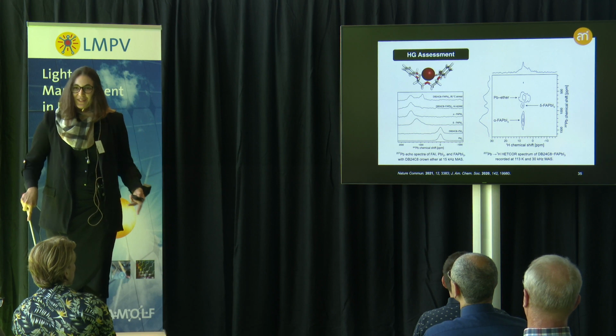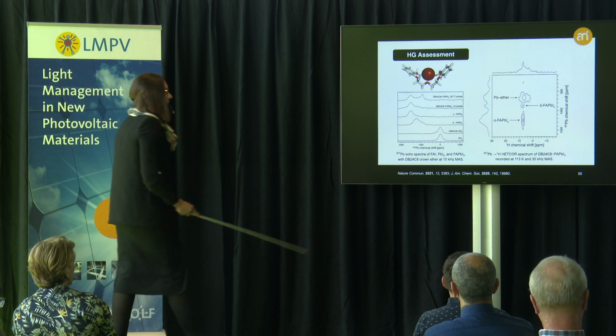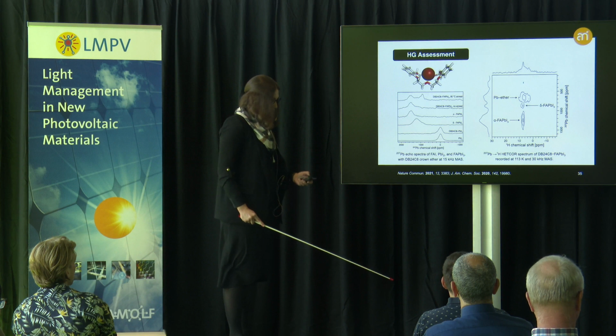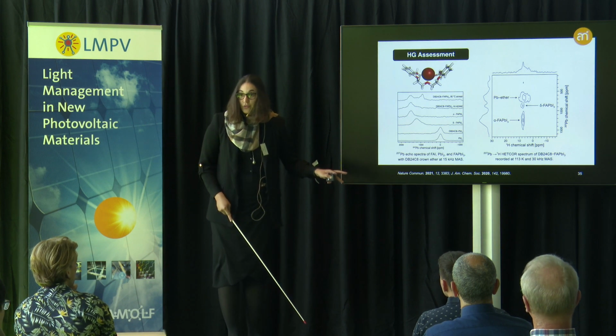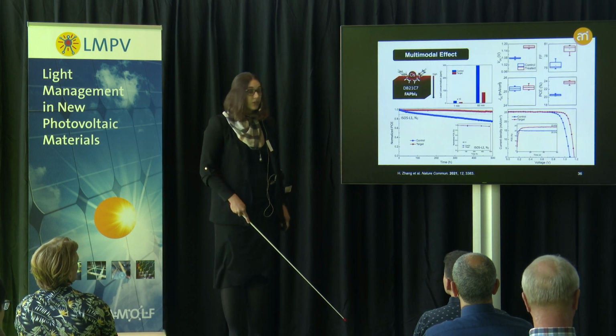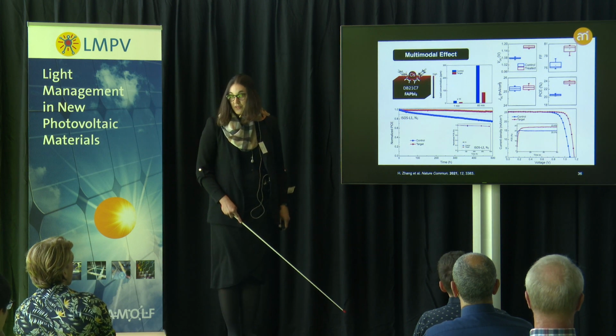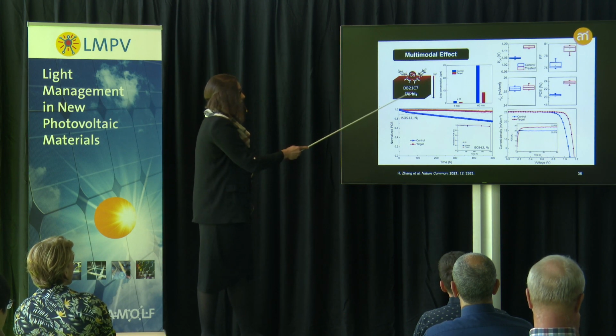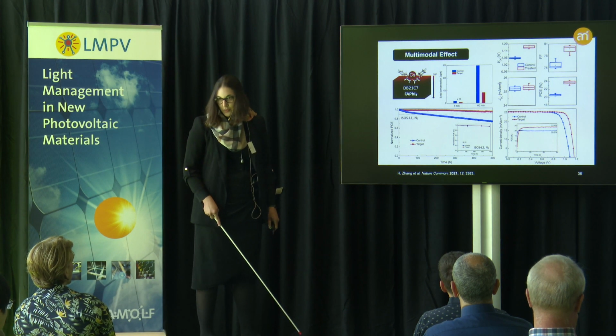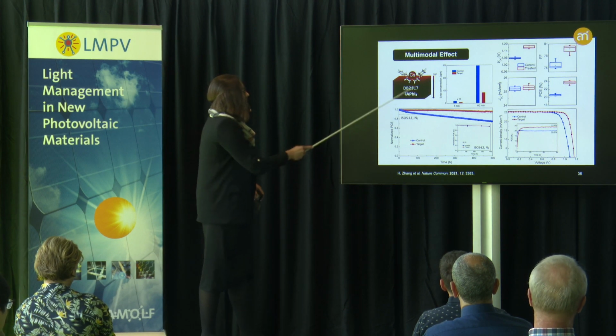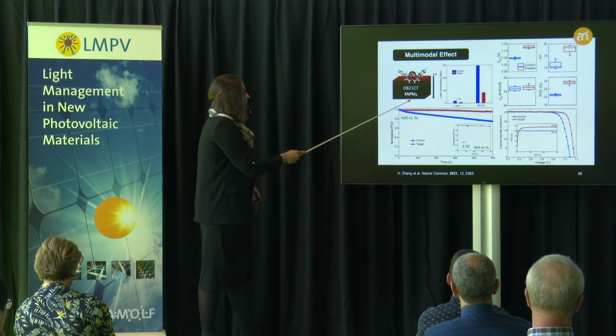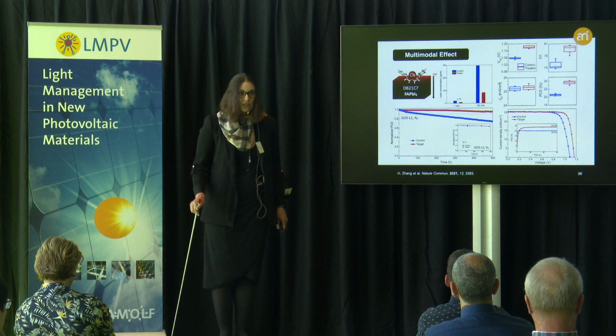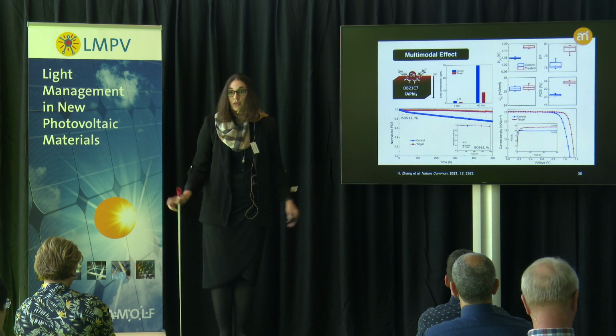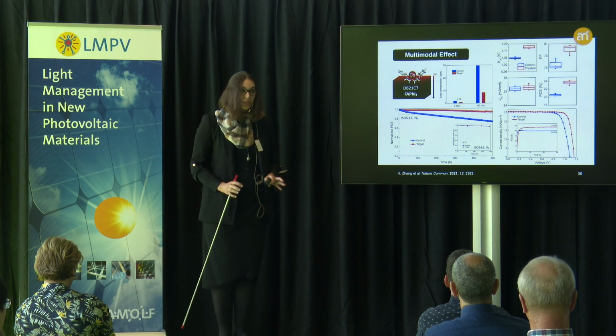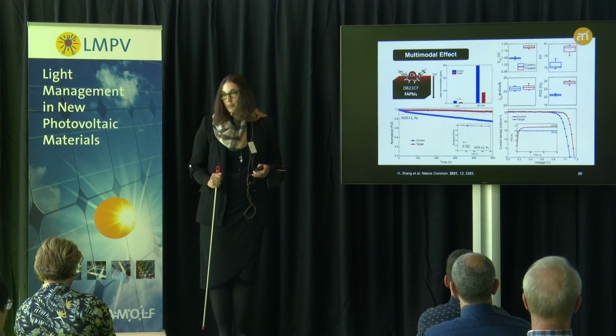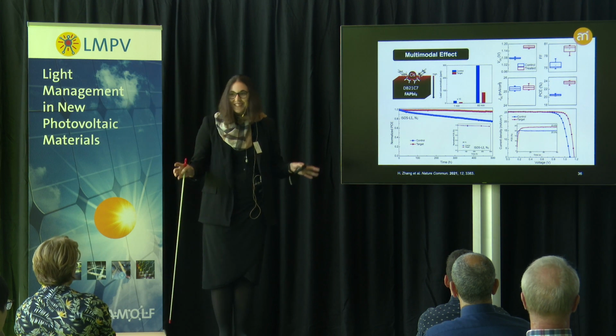Now, the capacity of this system, importantly, to competitively bind both A-cations and lead cations offers the possibility for it to serve as a molecular vehicle or a shuttle to deliver specific ions within the hybrid perovskite framework, and this particular cesium cations, which in fact were used for this formamidinium lead iodide perovskite composition most of you must be familiar with, which is one of the most attractive ones when it comes to the ideal optoelectronic characteristics